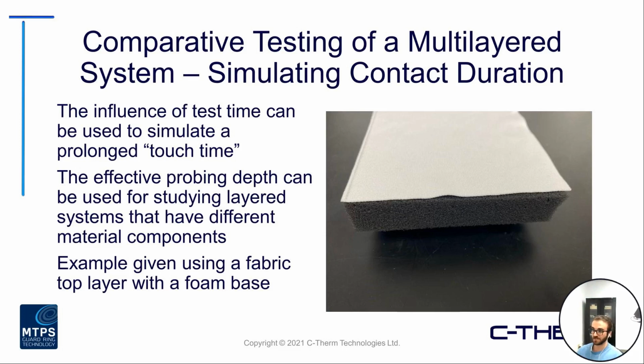Now, of course, there is obviously interest in testing a multi-layered system and understanding how that can play out if you do have different layers. You do need to be understanding of how the method has certain assumptions with respect to layered structures and how that heat pulse will propagate through these materials. But to do these types of studies, this more research and development application of simulating contact duration, we can get some very interesting results by doing different studies of the effective probing depth as a function of test time. In this example, we're looking at a structure that has a textile fabric on top of the foam. This is the same foam that we showed data for a few minutes ago, but we'll take a look at how varying the test time can give you some interesting results and may tell you a little bit about the sample that you're looking to work with.